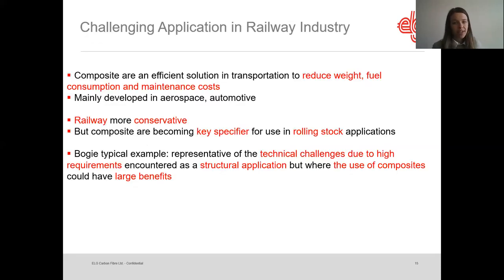To summarize the products and where they can be used: milled fiber and chopped fiber can mainly be used for injection molding and thermoplastic overmolding. The 100% carbon fiber non-woven mat can be used for vacuum infusion, RTM, and prepreg out-of-autoclave compression molding. The hybrid non-woven Carbiso TM can be used for thermoplastic overmolding, compression molding, and preparing organo sheets. I'm now going to show you a proper example — a project I've been working on for the last few years in the railway industry.